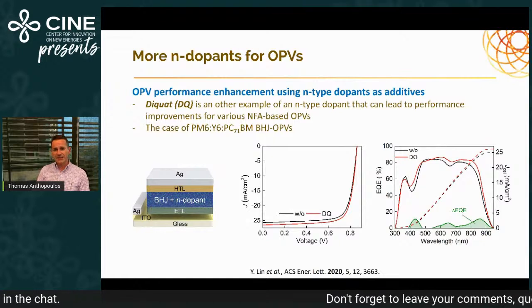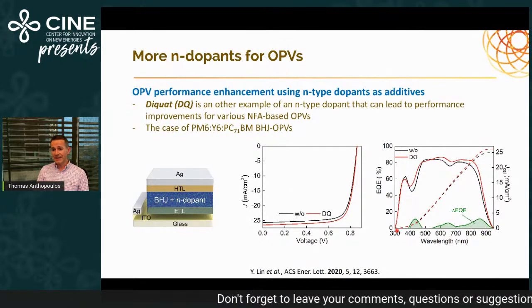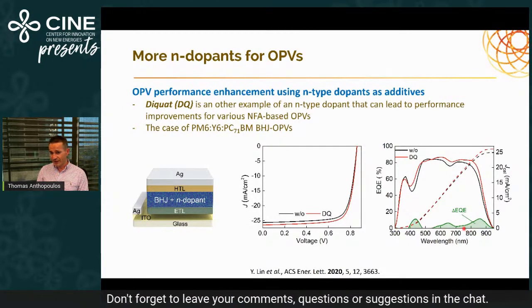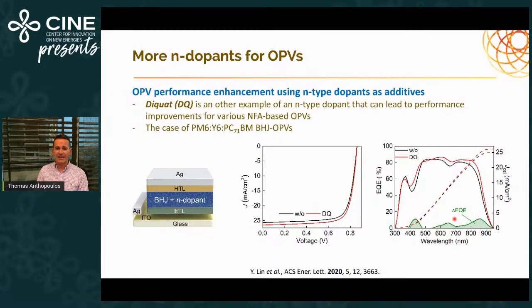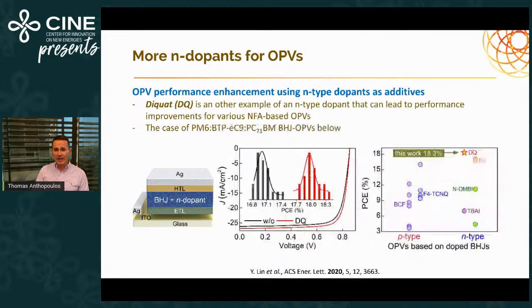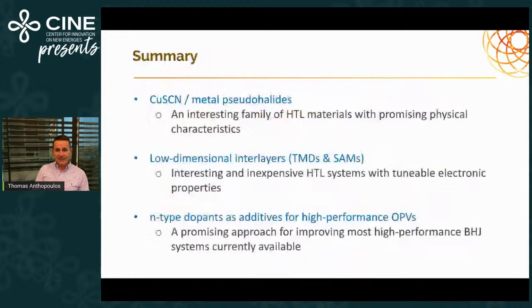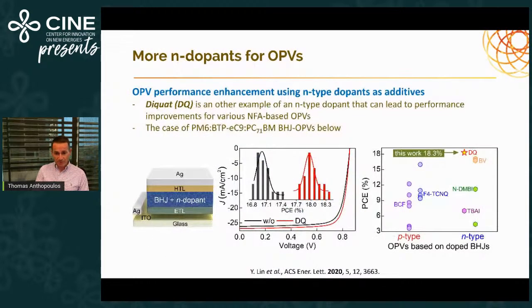So making devices, we saw that we can enhance the EQE across the spectrum at different parts of the electromagnetic spectrum. So essentially this green highlighted region shows where the gain is coming from for the current we observe in this JV curve under standard 1 sun illumination, and essentially allow us to reach an efficiency of 18.3%. So this paper was published a few years back. Since then, before I finish, we've been able to combine doping with other interlayer technologies and push this efficiency even further.